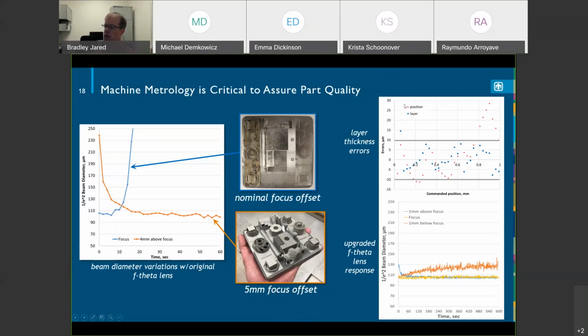Some other work we've done is the work on the top right here, which is actually looking at layer thickness, which was not something people look at very often. You see people talk about the laser and velocity and power and beam size and shape and all this, but we've actually found that the layer thickness has a very large impact on the material properties and also the reliability of the part.